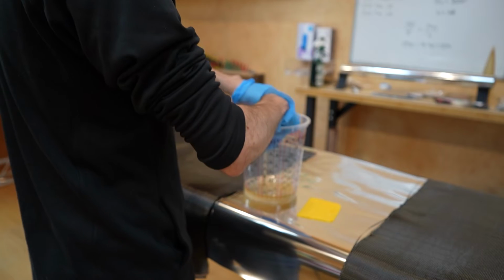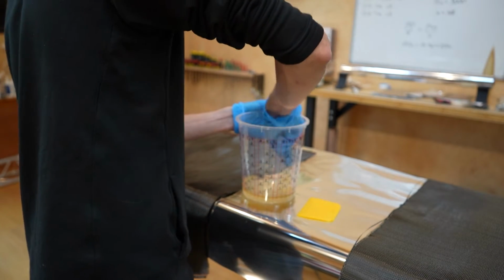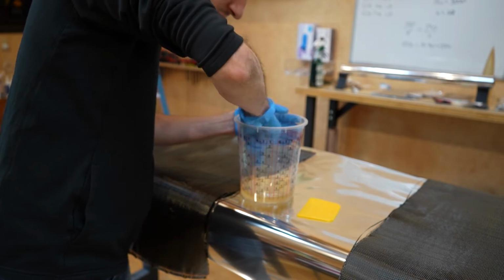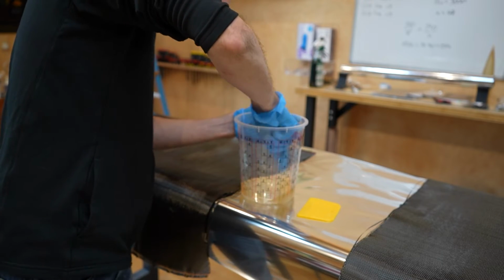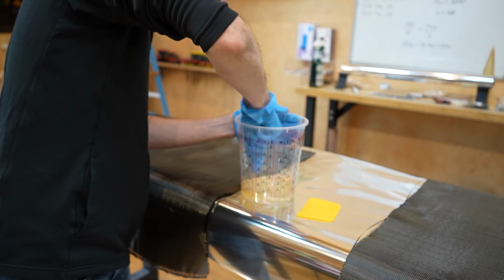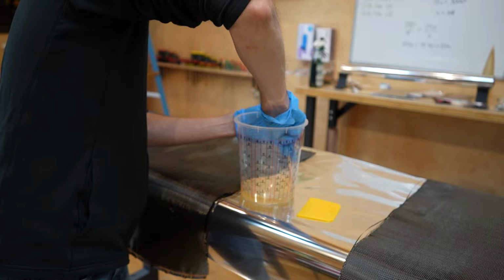Once I mix the epoxy, I weigh it out. I'm targeting a 1-to-1 ratio between resin and fiber. Typically, you'd want to have slightly less resin than fiber in your layup by mass. However, I'm going to perform a step later to help squeeze out extra epoxy, so I'm starting with a little extra epoxy now.